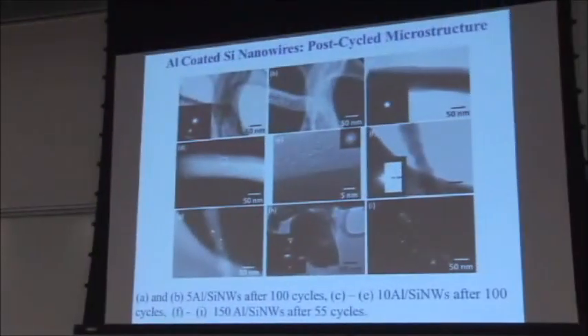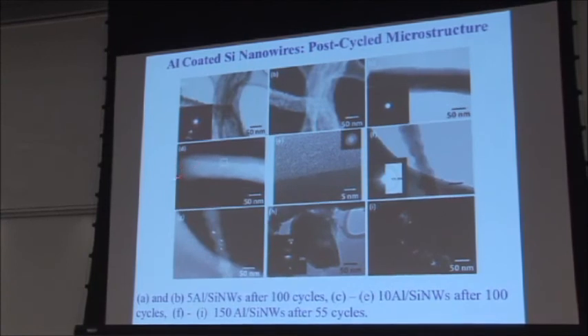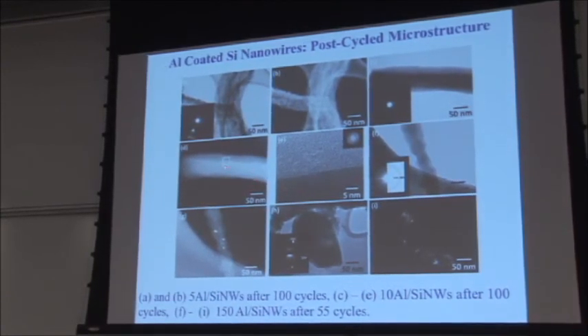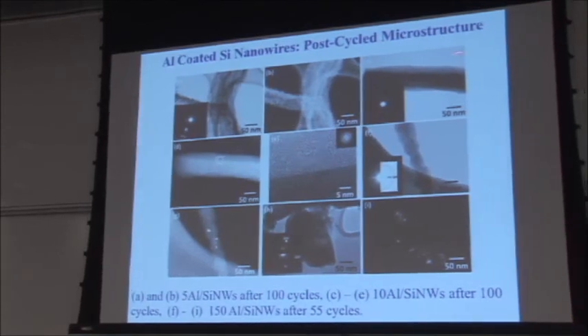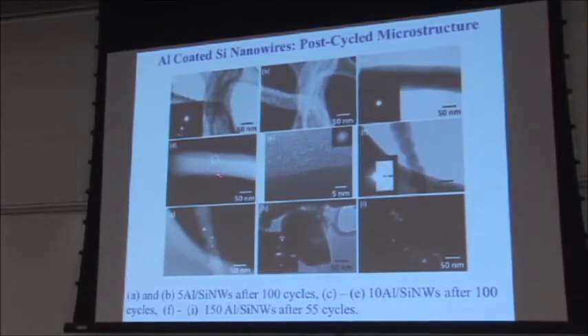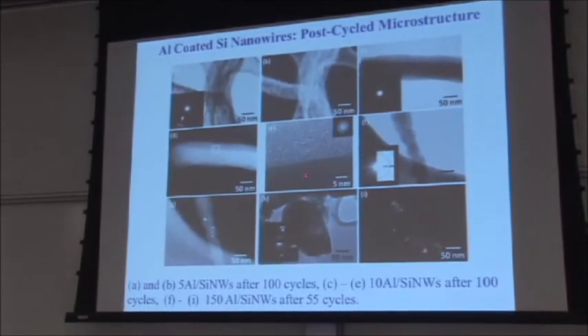So when you do the TEM analysis, this is the bare. Actually, so this is the 5 nanometer, so this is the thin coating. Things, again, start to kind of separate. It's all amorphous in the delithiated state. If you look at the 10 nanometer coating, the aluminum coating on the silicon is still intact. So you have your aluminum coating, you have your silicon core. If you look at the interface, it's quite continuous. These are all, by the way, taken in the delithiated state.